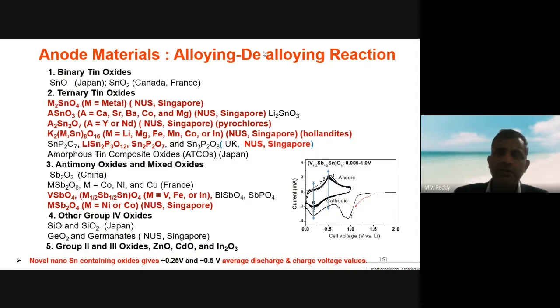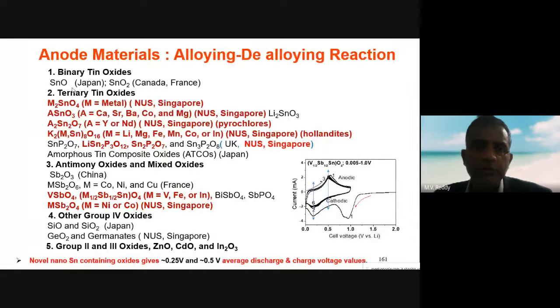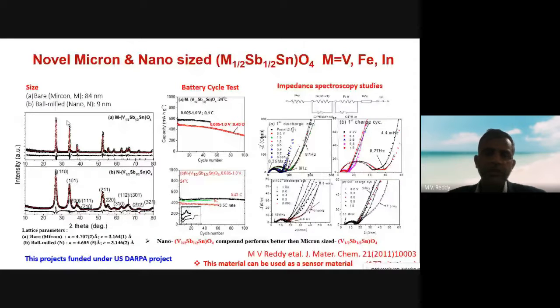So these are the tin-based systems. I think I told you about this early report from Japan, tin oxide. Later, from our group in the US and Singapore, we contributed a lot of interesting new materials, reported for the first time, for example these cubic type structures, I think perovskite, pyrochlore and hollandite, etc. The idea here is the tin matrix element, for example these tetragonal type structures. The discharge voltage is 0.25 and the charge voltage is 0.5 volt, etc. So this is one example of the new materials.